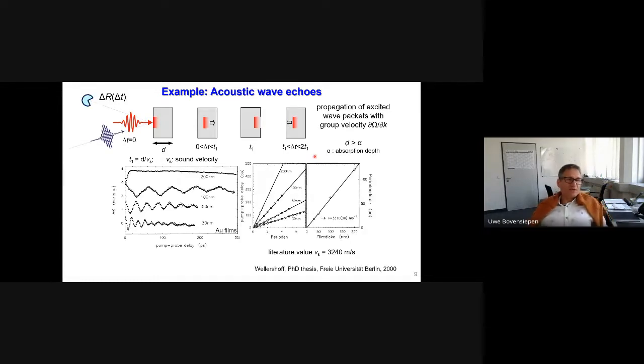And you can measure this in a rather simple linear reflectivity pump-probe experiment, where you monitor the change in reflectivity as a function of pump-probe time delay. This is done here with picosecond time resolution. And if you change the thickness of that film, these are gold films, you find that the thicker the film becomes, the longer the period in this echo is